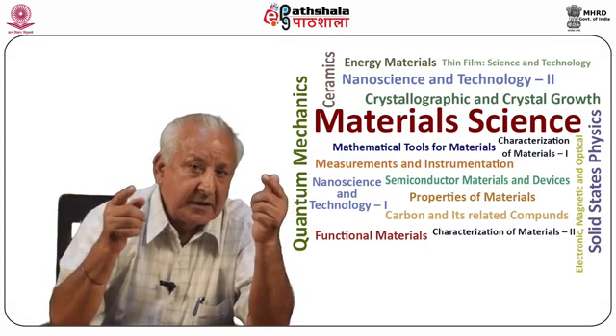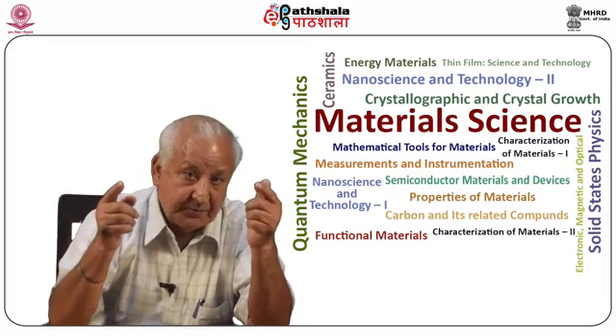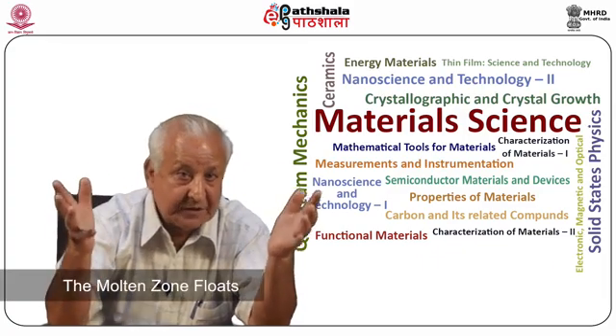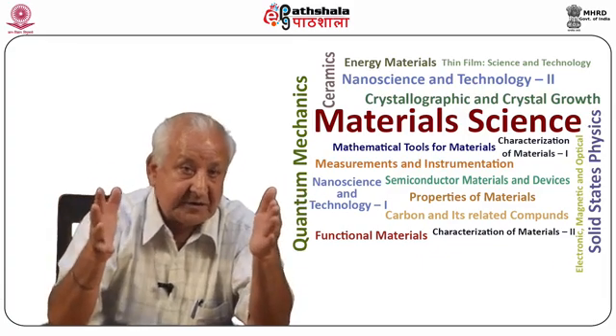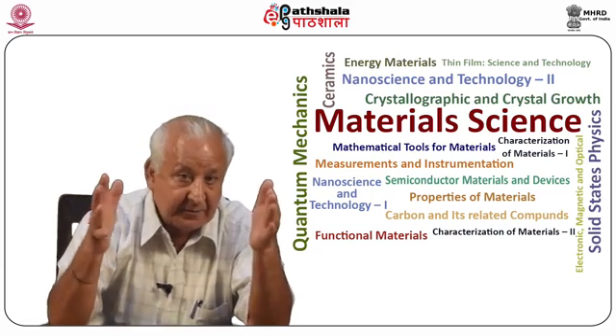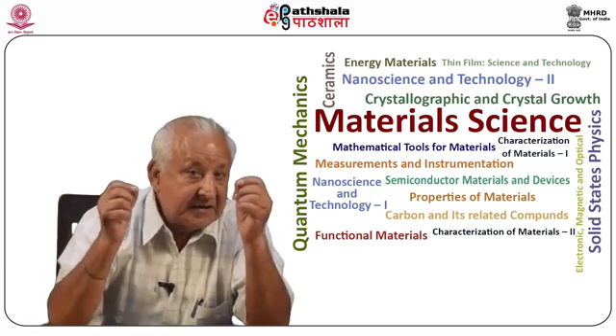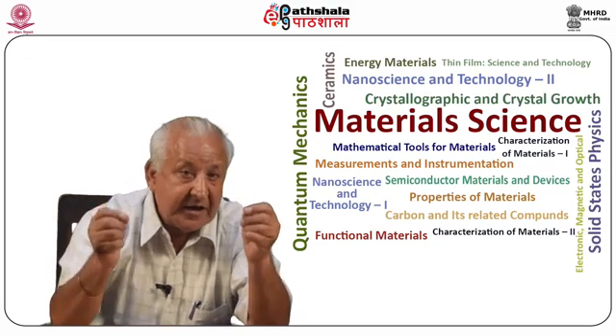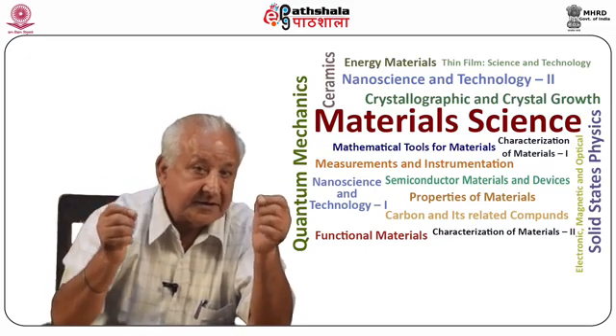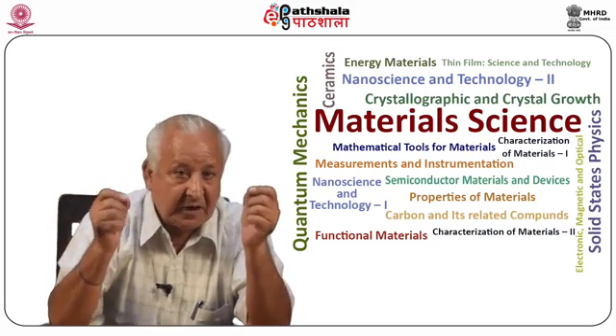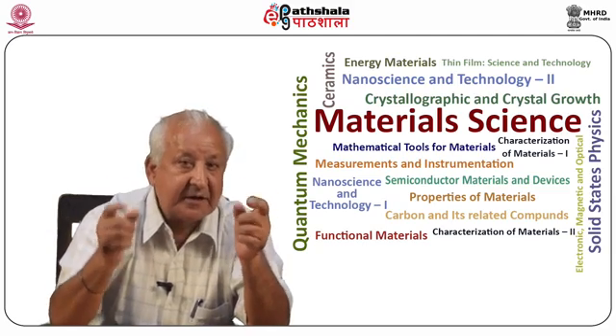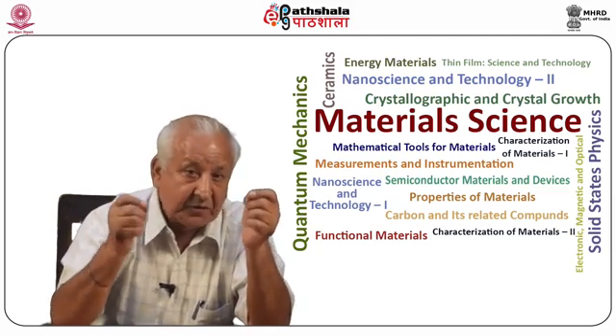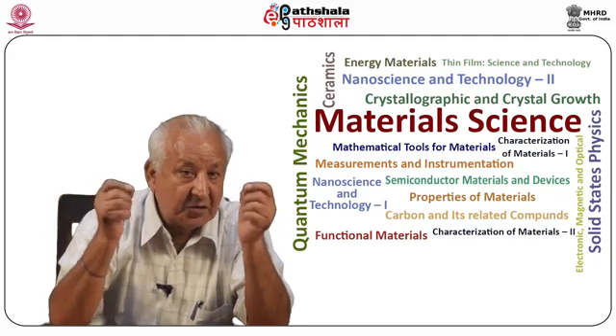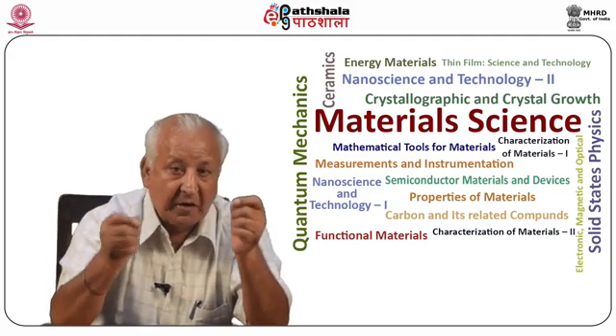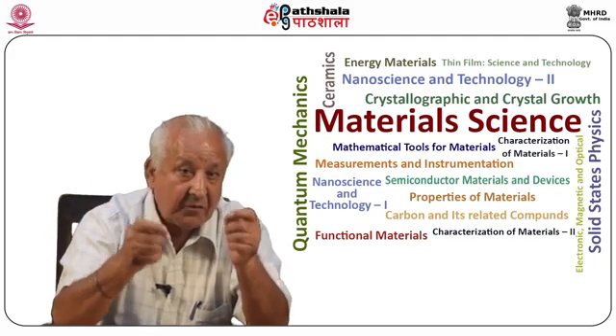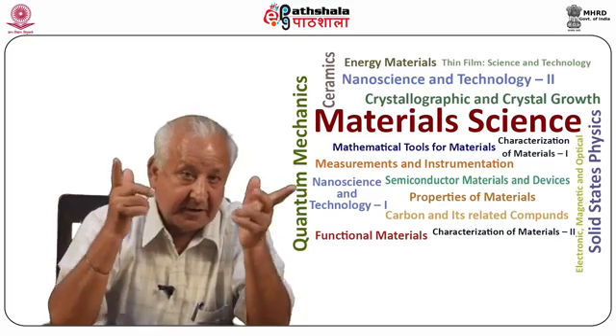This technique does not require any crucible. The molten zone floats between two solid parts of the rod held in place by surface tension. Since it does not require a retaining crucible, the technique has the advantage that possible contamination from the container is avoided. It is used for the growth of silicon, which is the only material grown on a very large scale, around 1,000 tons per year.